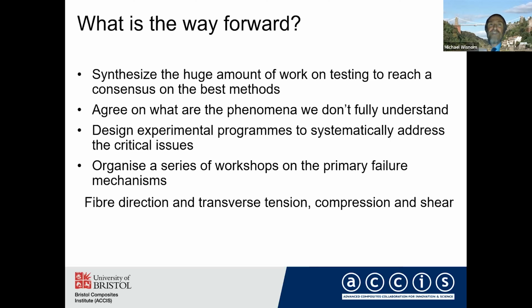If you're talking about really well hybridized, very well mixed materials, then I think the behavior can be very, very good. If you're talking about more chopped prepreg and things at that level, then clearly you have scope for localized delaminations and failure between the platelets. So that can give you additional failure mechanisms, which clearly need to be taken account of.